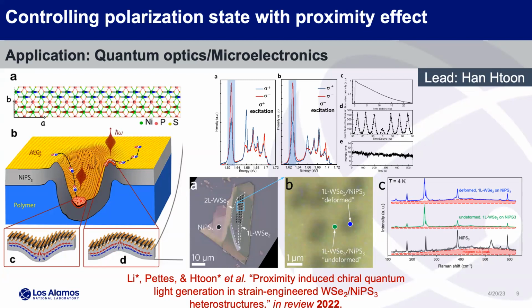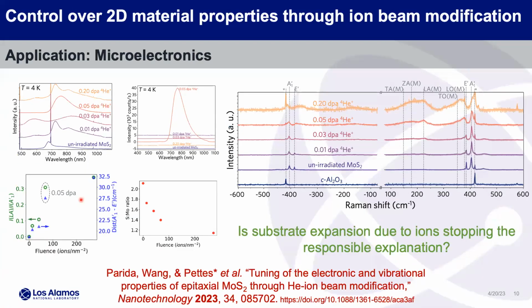Another thing that we're doing that ties in with microelectronics is we're trying to dope these 2D materials with low energy ions. This work is not low energy ions, but that's where we're trying to go. We have a facility called the Ion Beam Materials Laboratory at Los Alamos that's part of CINT. I'll have a slide towards the end. That facility has a tandem accelerator that can go up to, I forget the highest, but we were using about 18 mega electron volts, and it can go higher than that.